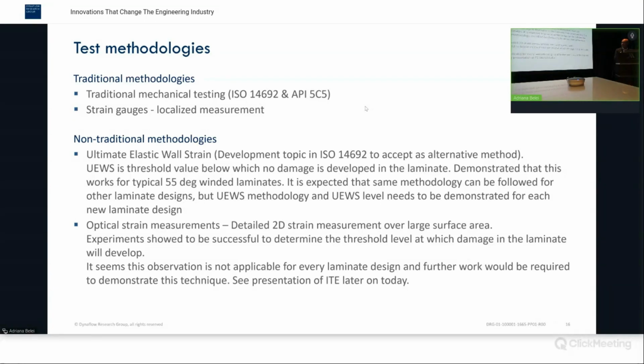The optical strain measurement, we found that it worked very well for plus minus 55 wound angle composite materials. So I will show you a picture in the next slide. We changed the design during the project. So we started with a plus minus 55 system, and we changed that to a 25/60 angled system. And with that design, we couldn't find reasonable results using the optical strain measurements.